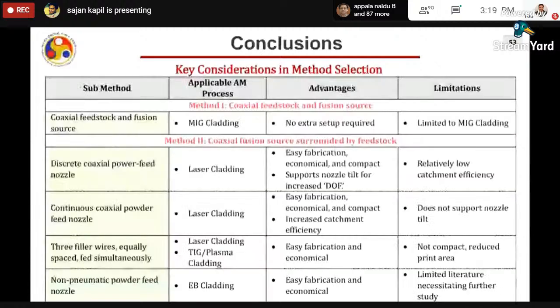Just a summary, I'm going to tell the limitations and the advantages. Method 1, which is coaxial feedstock and fusion source, is the best method, but only limited to MIG welding. Method 2, where the coaxial fusion source is surrounded by feedstock, means center laser or center electron beam surrounded by feedstock, can be of different types, like discrete, multiple nozzles you can feed, but relatively low catchment efficiency. You can use conical form of powder, but in that case, you cannot tilt the head. If you tilt the head, the density on the cone will be different.